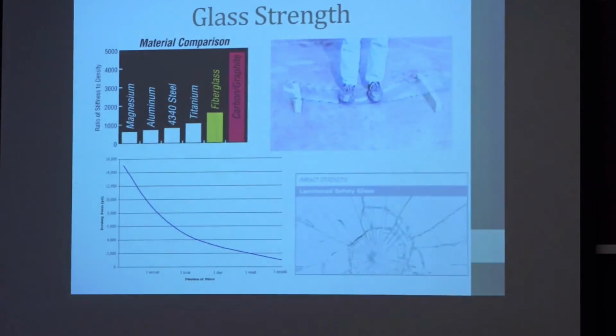What happens is when you first make the light bulb or form the glass, it's got a very smooth surface, no small flaws. And remember, the fracture mechanics of glass is such that a few, 100 micron flaw and all of a sudden you've lost 90% of your strength. Well, it turns out the problem is the sodium and potassium oxides in the glass are attacked by the humidity in the air. So if I want to make something out of good fiberglass, I got to make my glass fibers and coat them with that plastic within an hour or two, or I'm going to lose most of the strength of those fibers. When those fibers first come out of the fiber machine, they're as strong as steel. They have no defects. But once the humidity attacks them, then I have little flaws, surface flaws, and fracture mechanics tells me I'm going to have lousy strength.